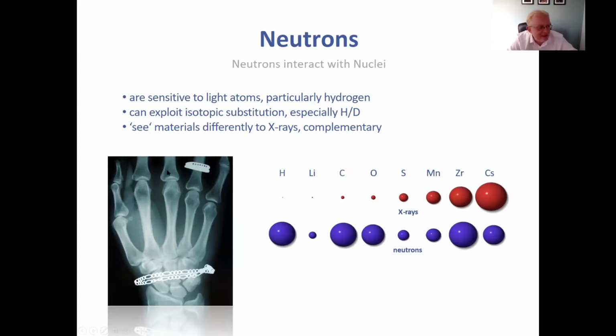You can see the bones, and you can see her jewelry very, very clearly, because X-rays scatter proportional to the square of the number of electrons around the nucleus, whereas neutrons interact with the nucleus, and therefore the scattering doesn't depend upon the atomic number. And so the way to compare the two techniques is that X-rays are very much like, well, an X-ray, whereas neutrons are very much like an MRI scanner. And so you will see the soft tissue.